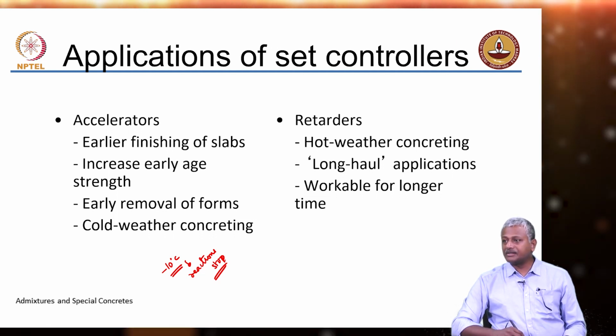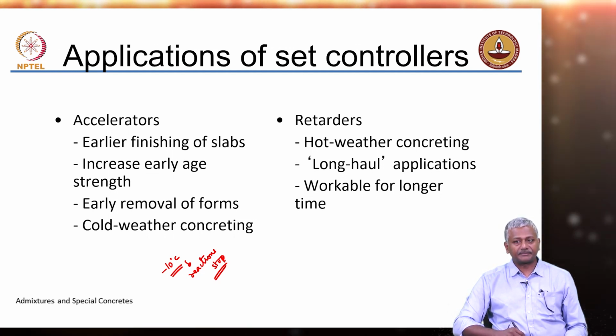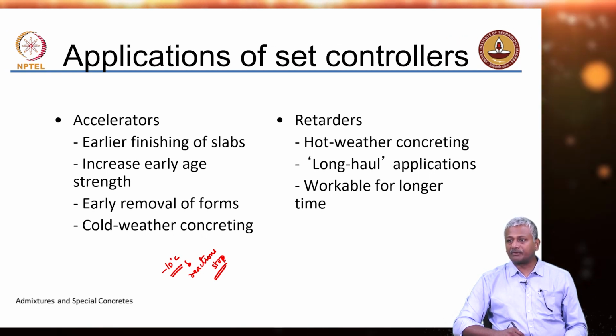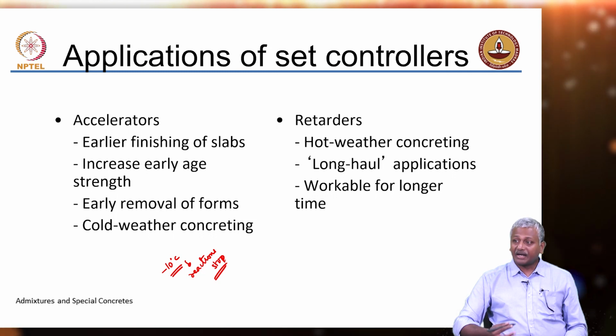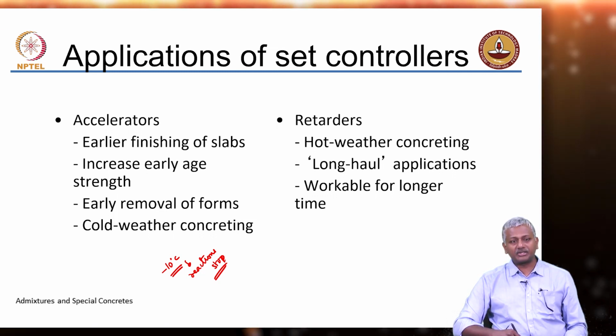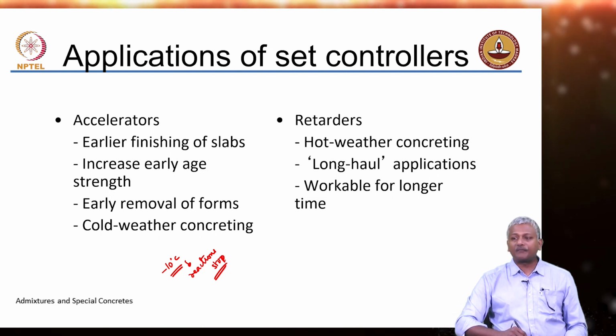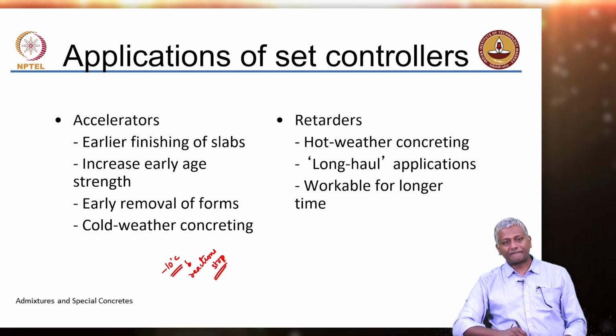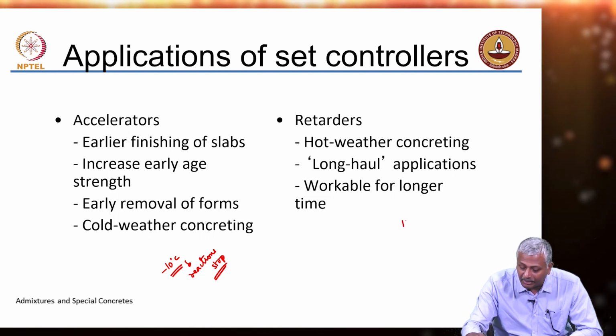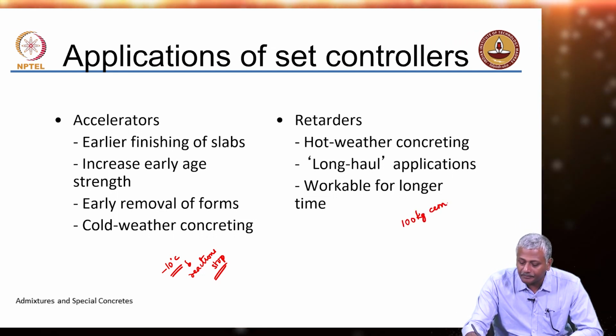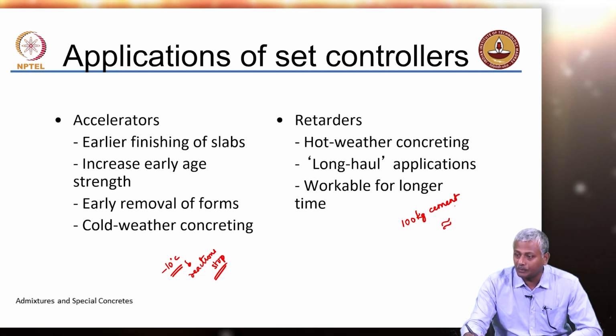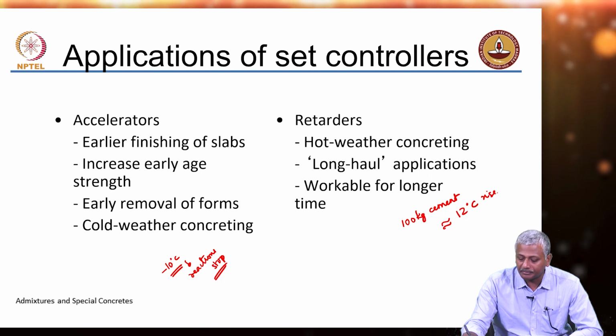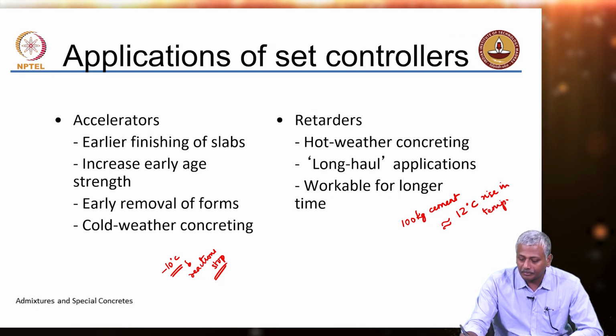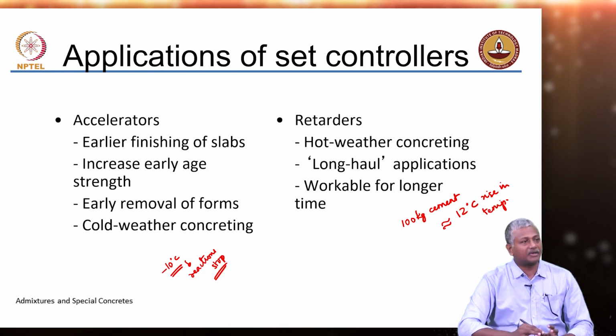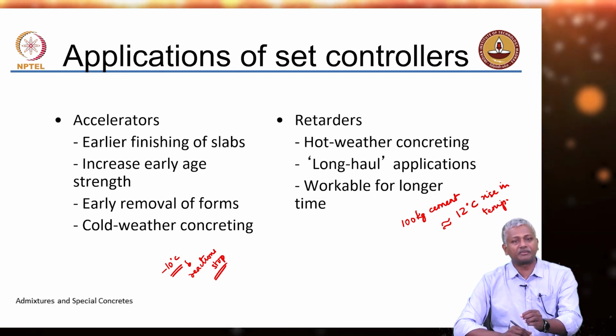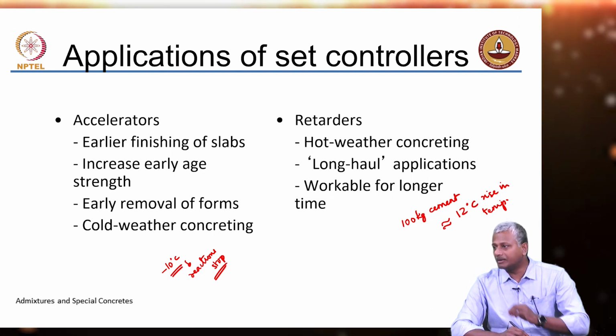On the other hand, retarders are used when you want to do hot weather concreting, right. When the temperature outside is 45-50 degrees Celsius, if that heat makes its way into the initial temperatures of the ingredients of the concrete, obviously the concrete temperature is going to shoot up like crazy. Okay, we will talk about mass concrete later, but in general about 100 kilogram of cement produces an equivalent of 12 degrees C rise in temperature. This is just a thumb rule. Okay. It can vary depending upon type of cement, of course. For every 100 kilogram cement you have in your mix, your concrete temperature will go up by about 12 degrees.